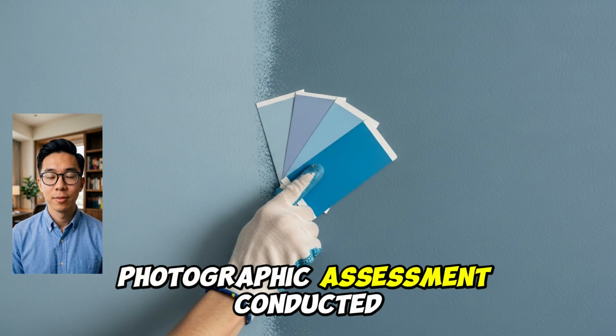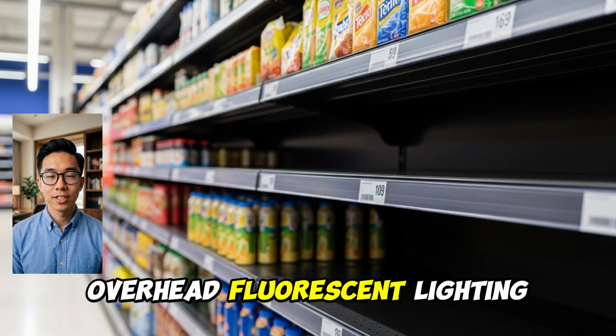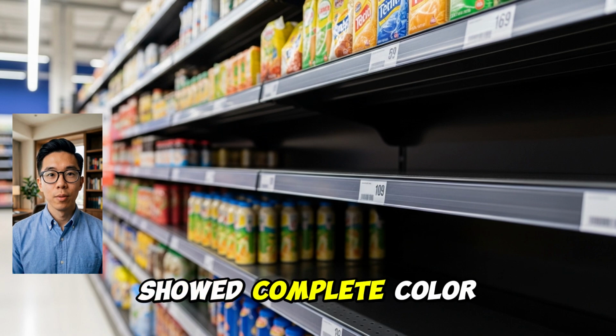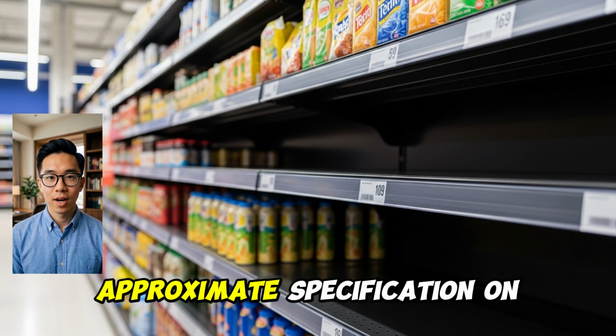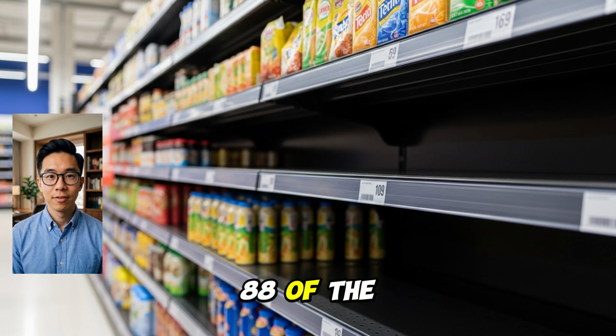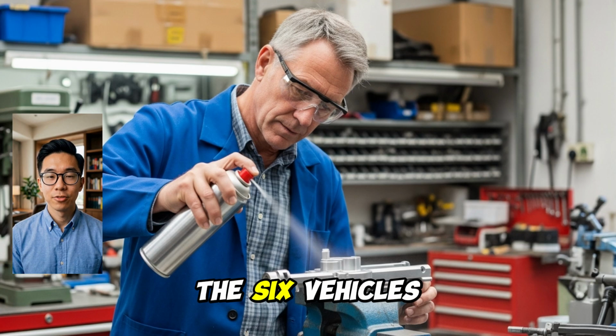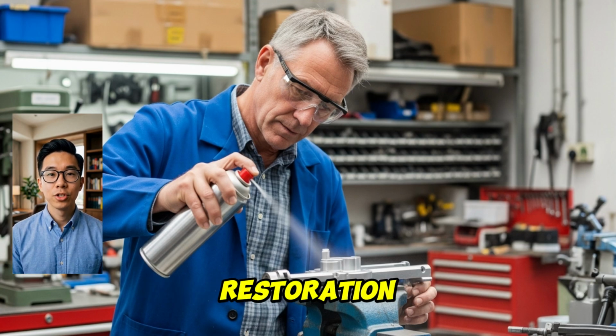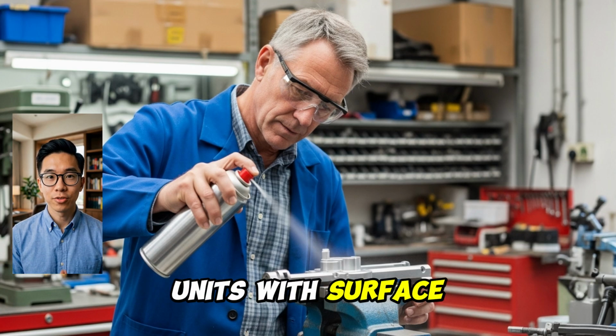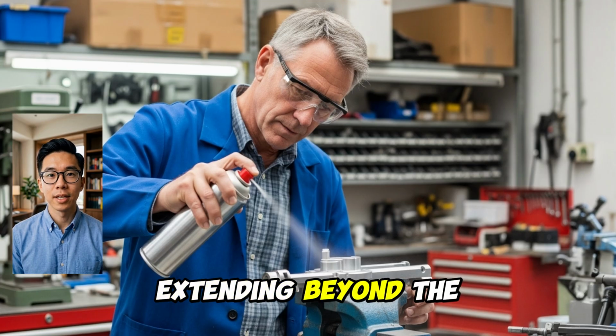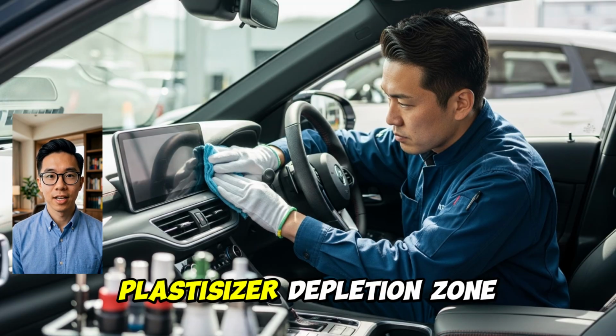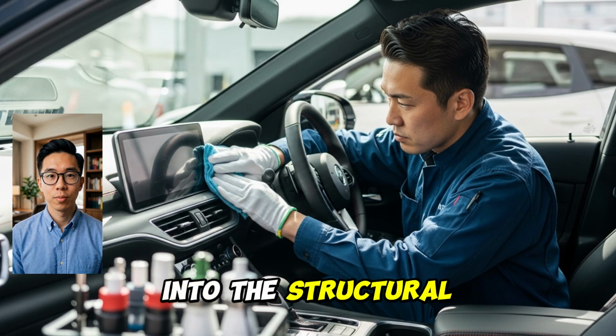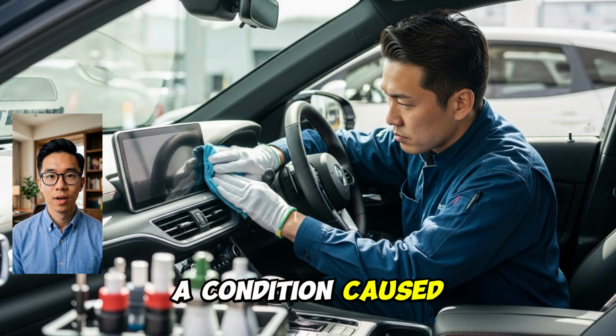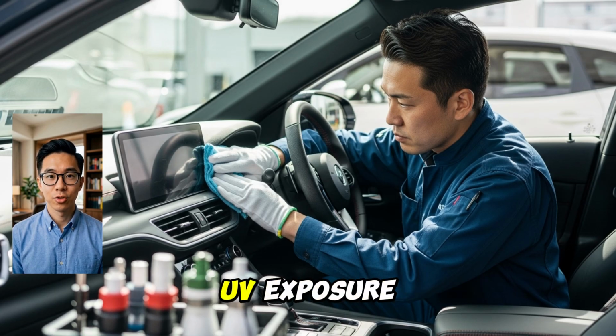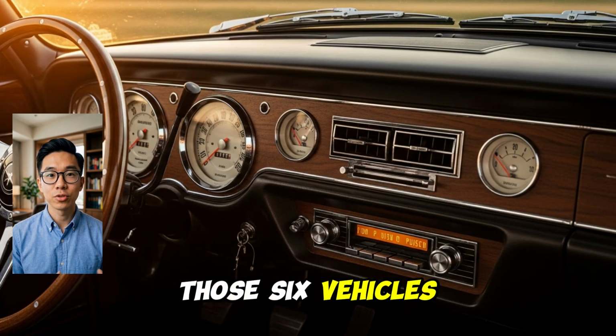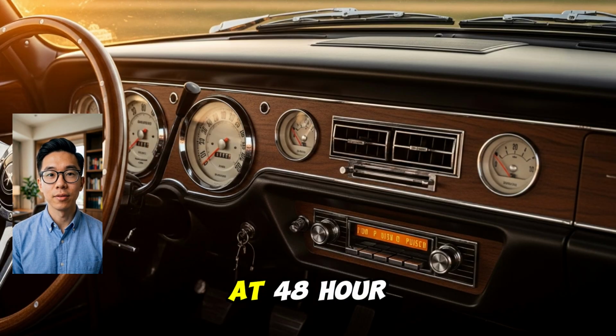Post-treatment photographic assessment conducted under standardized overhead fluorescent lighting at 800 lux showed complete color restoration to factory approximate specification on 88 of the 94 vehicles. The 6 vehicles that showed incomplete restoration were stage 3 units with surface texture degradation extending beyond the 0.4 millimeter plasticizer depletion zone into the structural polymer beneath, a condition caused by mechanical abrasion in addition to UV exposure. Those 6 vehicles required a second application cycle at 48-hour intervals.